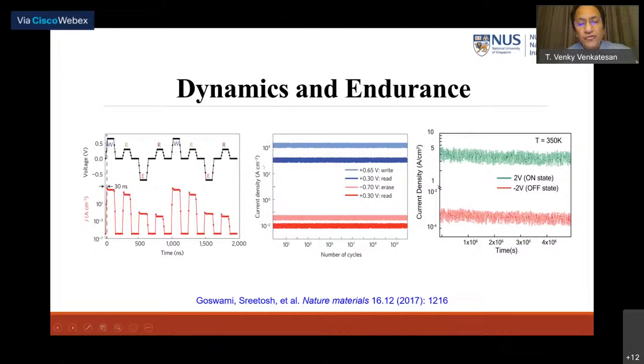Now, these are the different switch states. After every switching, these are the recorded switch states. And you can see they're absolutely rock steady. We have gone to 10 to the 12th cycle, and still all the states are absolutely preserved, showing the robustness of this memory. In comparison, if you had your thumb drive and you switched it this many times, by 10 to the 6th cycles, you start getting errors in the flash memories. And this is about 1 million times better than a flash memory, which is remarkable.